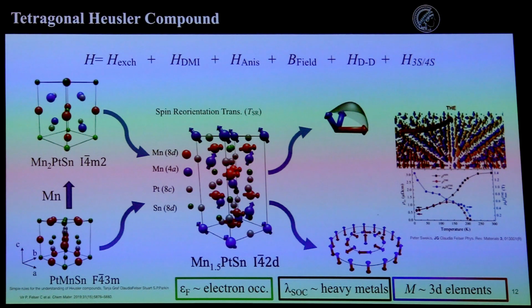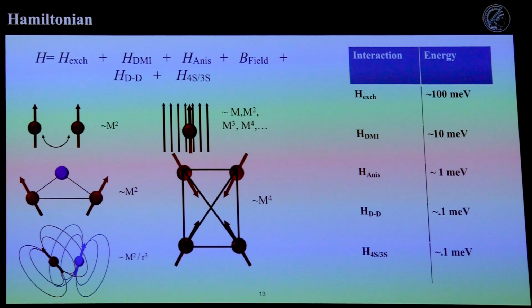And this all gives rise to this classical Hamiltonian that we were talking about. To continue, what is this Hamiltonian? Yeah, so we will go through this very slowly, and then through the results, we'll go a little quicker. So you have exchange. Exchange is something usually between two atoms that want to connect, collinear or anti-collinear. It's usually on the order of m squared. Then you have this DMI, which is due to some broken inversion symmetry and some spin-orbit coupling that causes a canting of the spins. You have this anisotropy, which has many different orders, but it says, hey, I want to align in some direction due to this field. You have this dipole-dipole interaction, and you also have this biquadratic interaction, which we don't discuss so much.